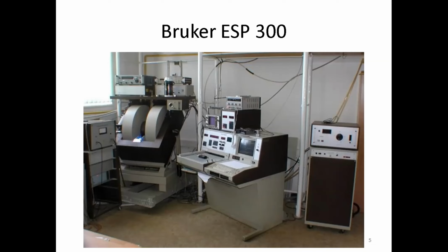The spectral parameters of 63,65Cu NMR in the local fields in chalcopyrite were measured on a TecMag Redstone NQR/NMR spectrometer. Measurement of the NMR line shape was performed using quadrature detection by recording the spin echo signal with step-by-step passage of the frequency range and signal accumulation. The EPR spectra of undoped chalcopyrite and palladium doped chalcopyrite were studied on a Bruker stationary X-band spectrometer ESP 300 in the temperature range 15 to 300 Kelvin. The masses of the samples were approximately the same.